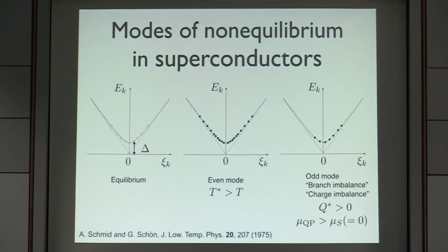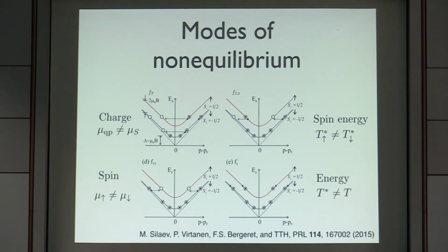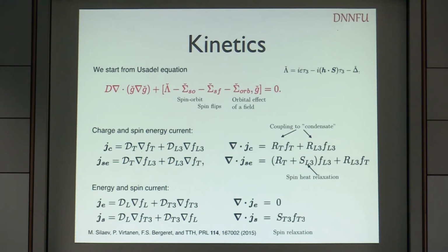The even mode is the so-called FL mode or heat mode, and the odd mode is the charge imbalance mode. These are the diagonal modes here. But when you include spin as a relevant variable, you also have two additional modes, the spin energy mode and the spin mode. Now if you do kinetic equations, you have to describe all four of them. The kinetic equations also come from the Usadel equation. We plug this Keldysh-Green's function into the Usadel equation and find the equations. These are basically the analogs of the Boltzmann equation for the superconducting case.